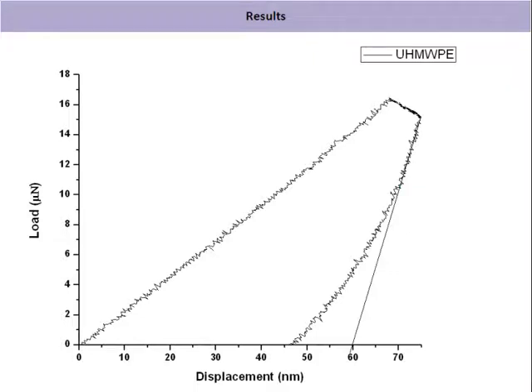These are the results. Ultra high molecular weight polyethylene and its composites are used for the study. Ultra high molecular weight polyethylene has been chosen as a reference material, and this is the typical load versus displacement curve obtained for it. Here we can see that the maximum attained load is around 16 micronewtons, and the maximum displacement is around 75 nanometers.